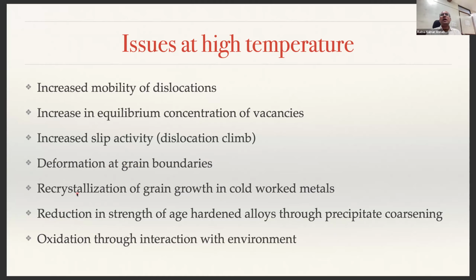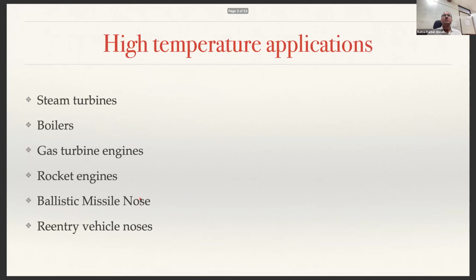Right? So then also you will have recrystallization and grain growth in cold worked material. That means the grains start growing in size because of the larger temperature, so diffusion takes place easily over larger distances, and hence grain size will increase. And there is oxidation, because at high temperature, oxidation will be promoted much more easily. So these are all detrimental effects that you don't want in materials when they are operating at high temperature. That is the reason why you need to understand the behavior of these systems at high temperature.